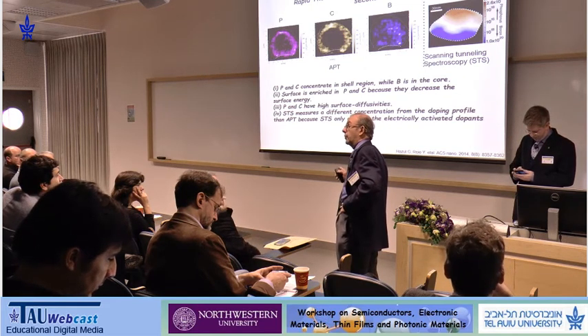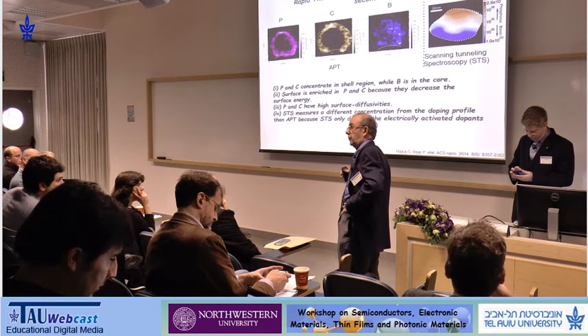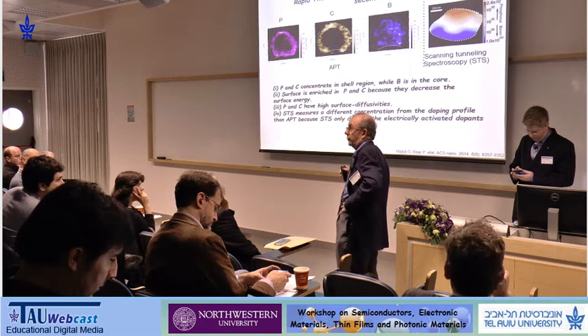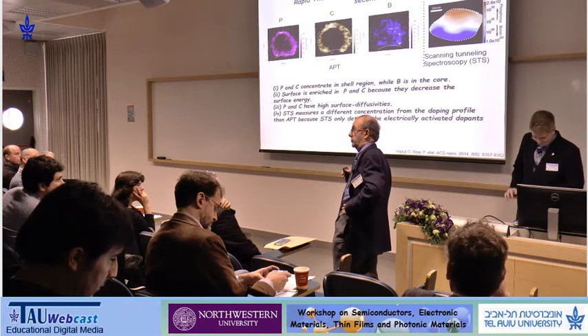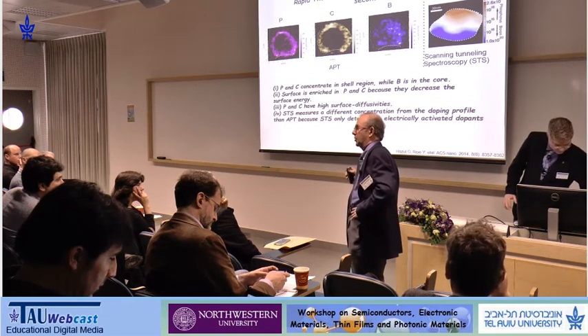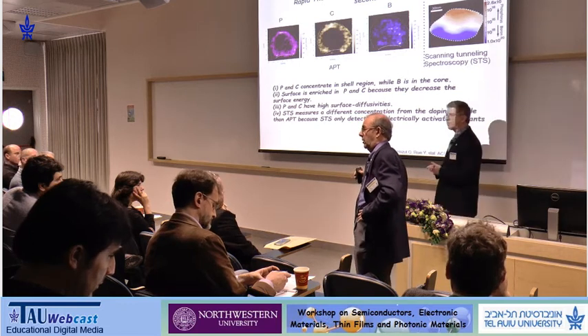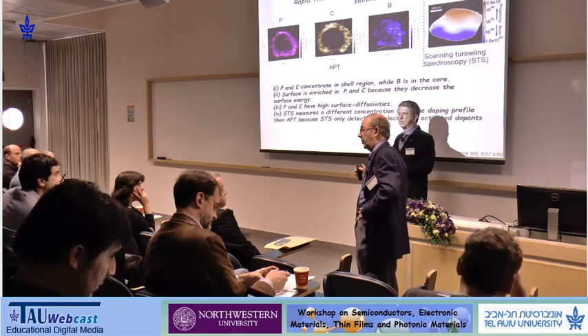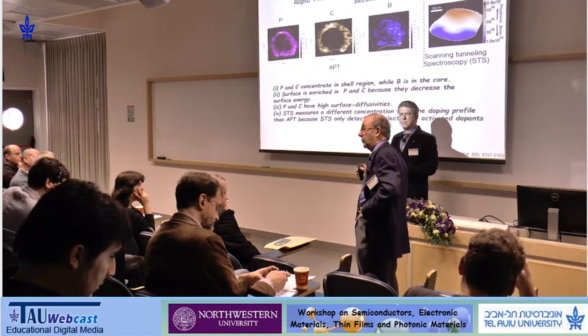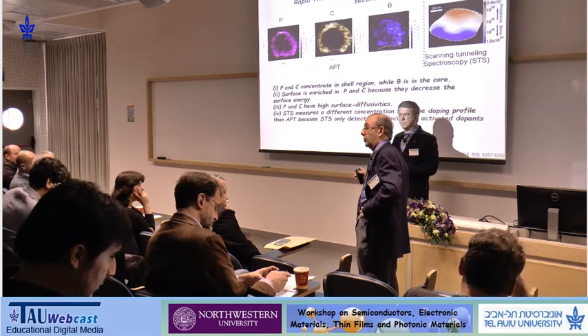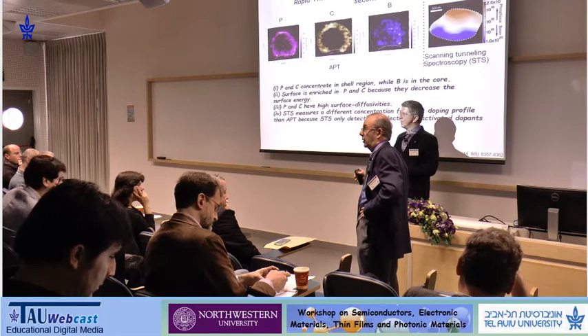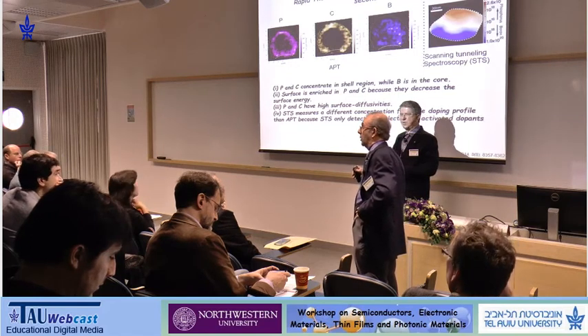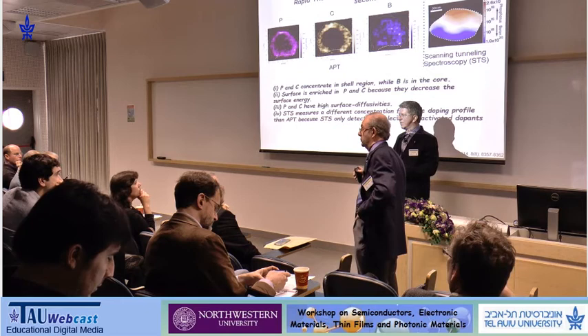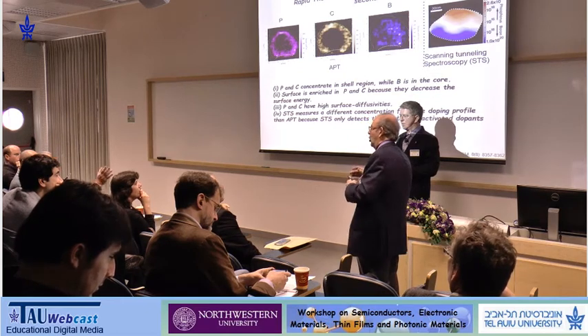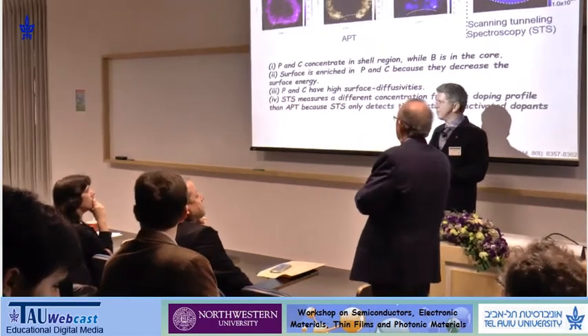I mean, they're grown on copper, right? And then we deposit from a sputter source. It's low energy sputtering. The atoms are sputtered from a nickel source, and then they hit the graphene with rather low energy. It's a nickel source? Yeah. So is it gallium atoms, or? No. So there's two things involved here.